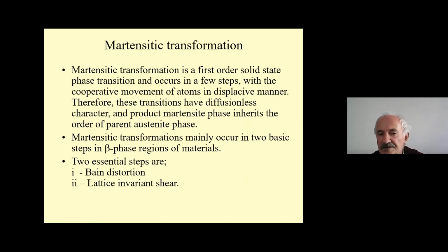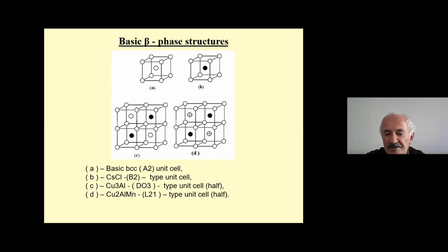Martensitic transformations are first order solid state phase transitions and occur in a few steps with the cooperative movement of atoms in a displacive manner. Therefore, these transitions have a diffusionless character, and the product martensite phase inherits the order of the parent austenite phase. Mainly, martensitic transformations occur in two basic steps in the beta phase region of the material. These are Bain distortion and lattice invariant shear.